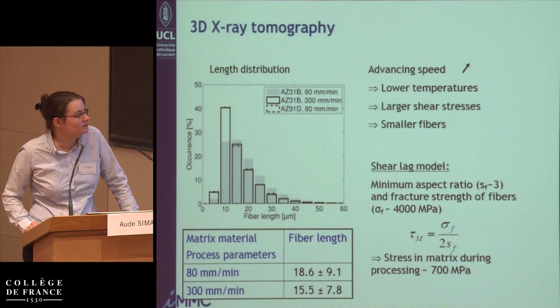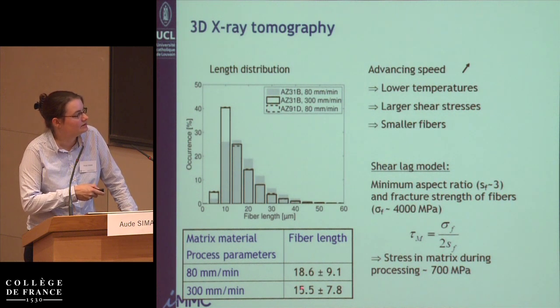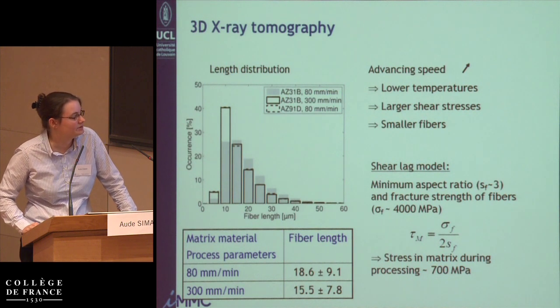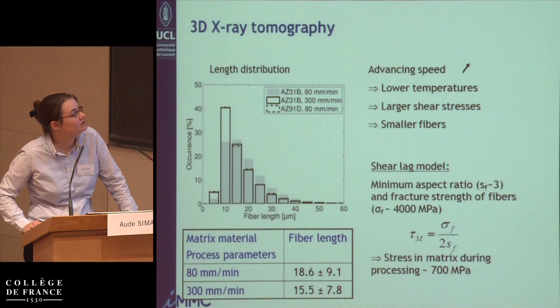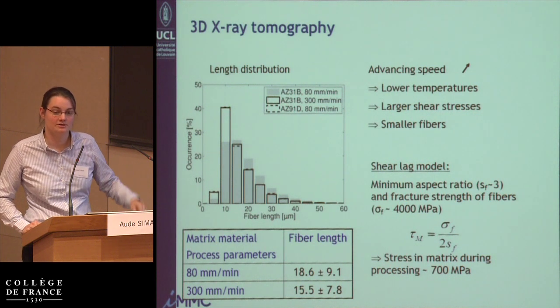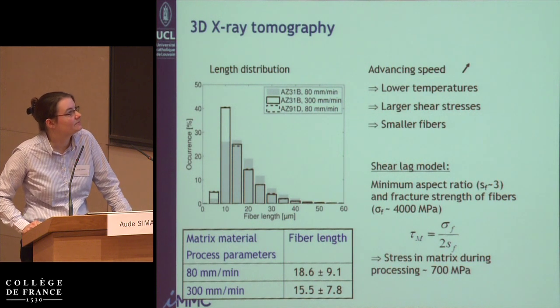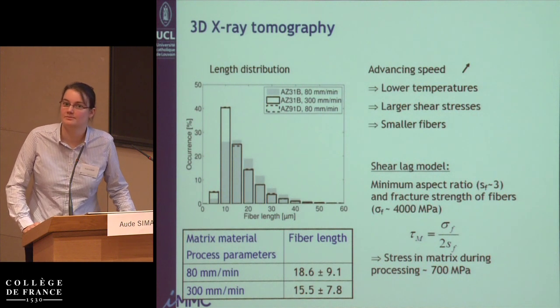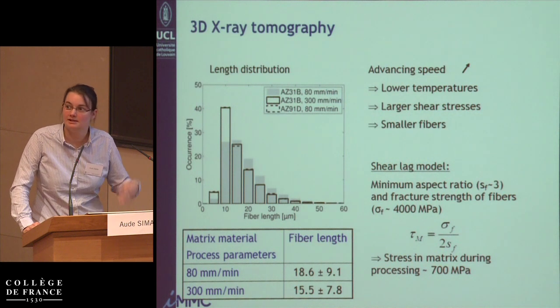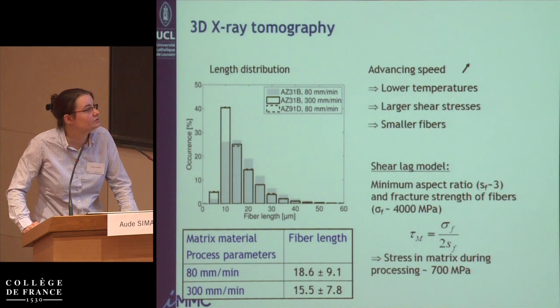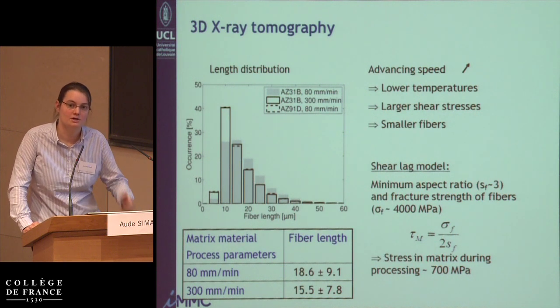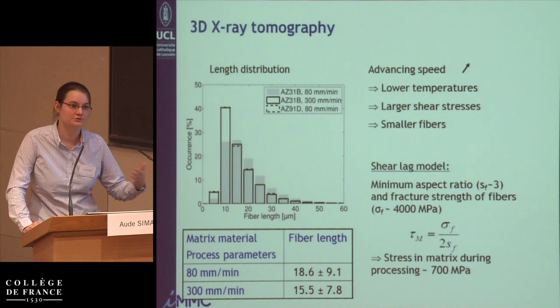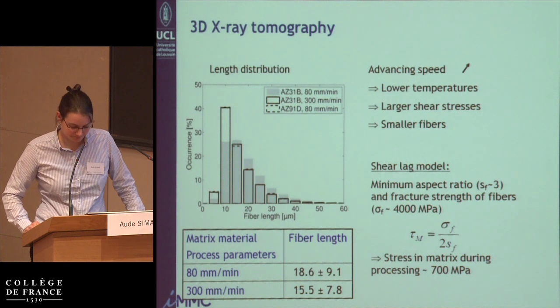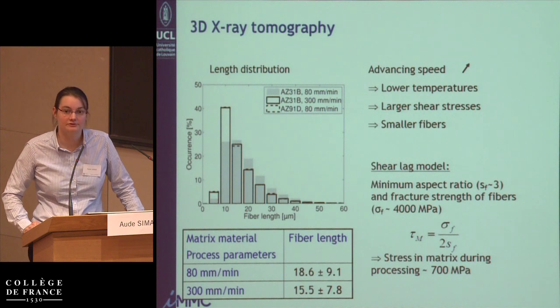Well, this is the fiber length decrease that you see when you have an increase in advancing speed. And also, you see here that we've tested another material which is a stronger matrix. So you have more aluminum in this magnesium matrix, and so it's a stronger material at the basis, and so we actually also have shorter fibers when we are using larger advancing speeds. So we can also tune the fiber length by the strength of the matrix, because of course the strength of the matrix has an impact on the behavior after friction stir processing.